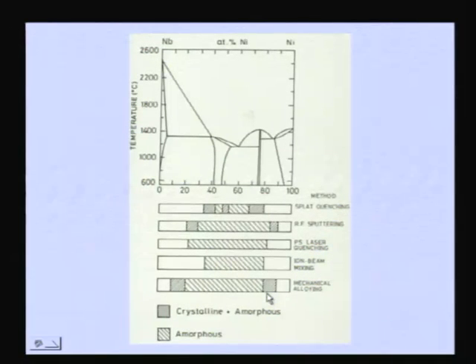An interesting thing is also that by the liquid metallurgy route, that means if you use rapid solidification, the glass formation always occurs near the eutectics, particularly near deep eutectics. Why? Because that is where the liquid is stable, and that is where the TG is close to that of the TL, and that is why we have talked about glass forming criteria such as TRG, the reduced glass transition temperature, that is very high at the eutectic temperature.